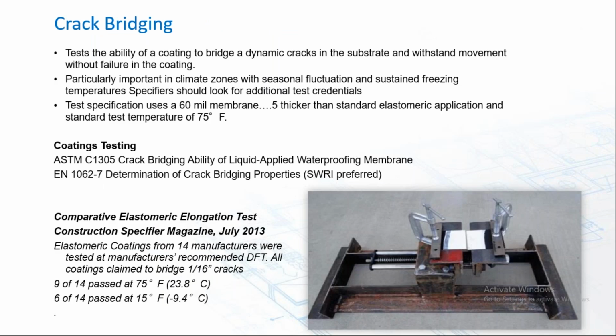So crack bridging is another interesting one here, and obviously an important test from the point of view of concrete. We know it is going to crack sooner or later, and it tests the ability of a coating to bridge dynamic cracks and withstand movement without failure of the coating. ASTM C1305 is a pass-fail test that just provides test results at 2 temperatures, freezing and at normal 73-degree Fahrenheit room temperatures, or 75, excuse me.